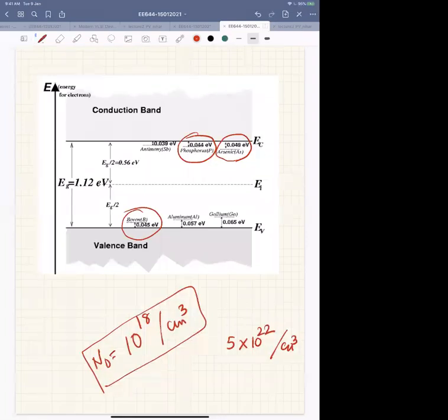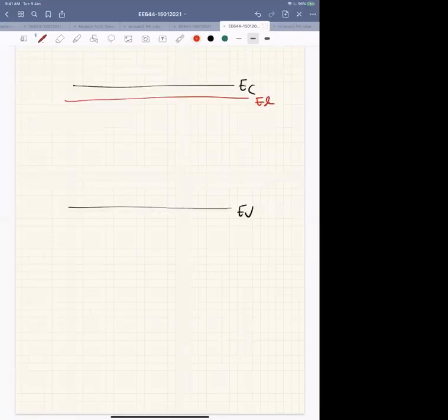If you go on doping more and more, let's say this is EC and EV. You have one defect state, ED, but if you go on increasing, it will form a band, slowly, and this band will increase and merge with the conduction band, and there we call that the conduction band. So in the very high doping case, your donor level and the actual conduction band of silicon will merge. That means this will become your conduction band. So that is called band gap narrowing.